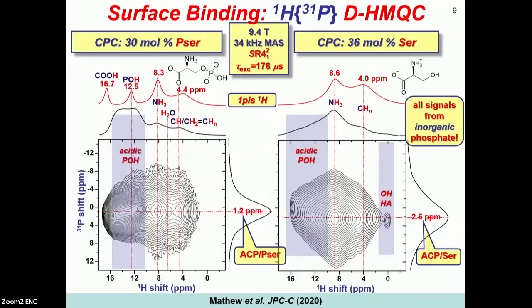So for the remainder, I will focus on talking about basically the interface between the organic molecules and ACP, and more precisely how the molecules bind at ACP. What you see here are dipolar-mediated HMQC spectra, proton phosphorus, which were recorded from cements that comprised either 30 mole% of phosphoserine or 36 mole% of serine. In the case of the serine-doped cements, since there are no organic phosphate groups, the correlation signals show unambiguously that you have protons in both aliphatic groups and primarily the amino group that are in close proximity to the inorganic phosphate groups of ACP.